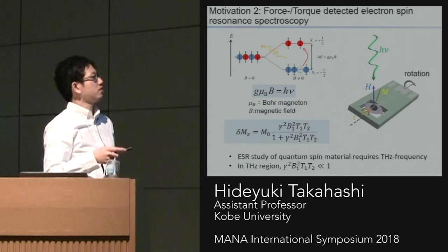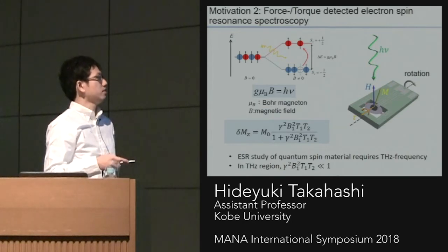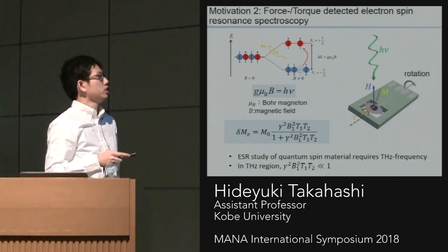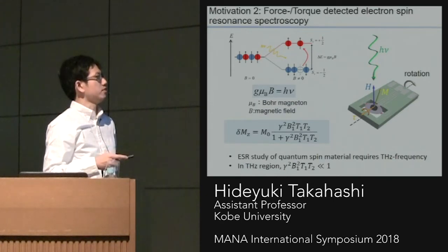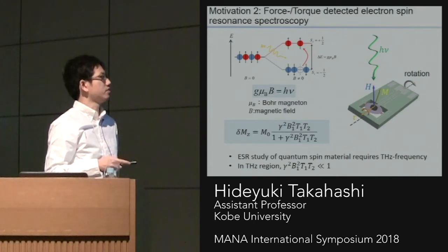The principle is simple. This is the ESR-induced magnetization change. This magnetization change occurs due to the spin flip transition of electrons. So ESR induces a spin flip transition, and it changes the occupancies of these spin states, so it affects the macroscopic magnetization.